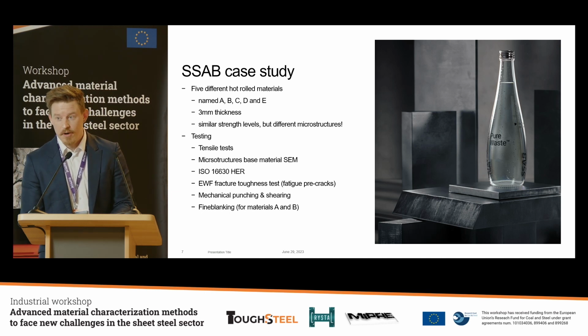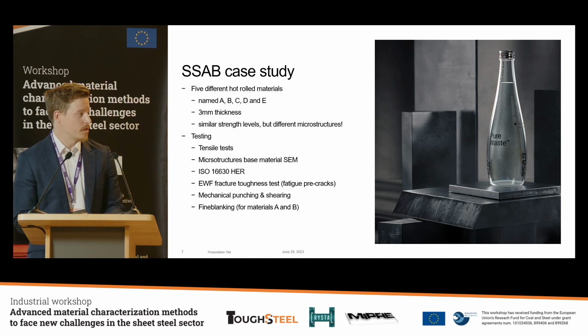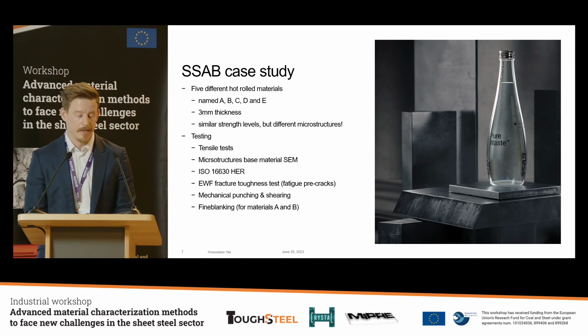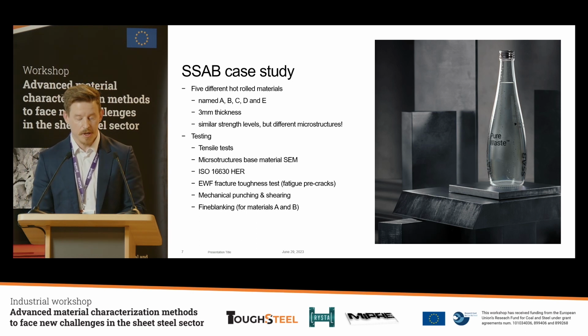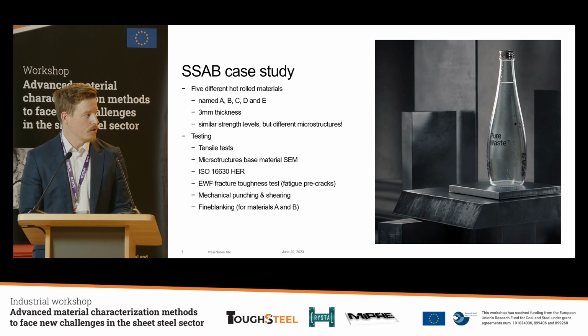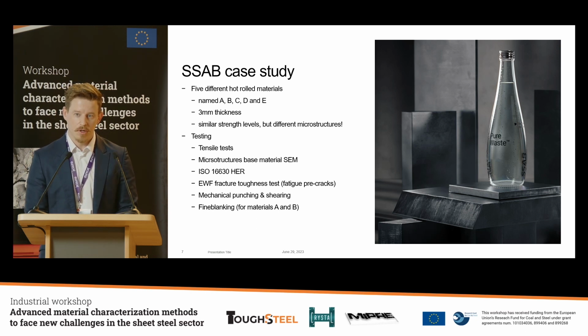The testing plan, of course, normal mechanical testing. I will show you also the base microstructures of these steel grades. We conducted also the ISO hole expansion tests, and here at the Eurecat also these essential work of fracture tests. Now we will present results with the fatigue pre-cracks, and hopefully in the future we have also results for the notched specimens. And then I will also show you some results on shearing, punching, and fine blanking tests for 2 of the materials.